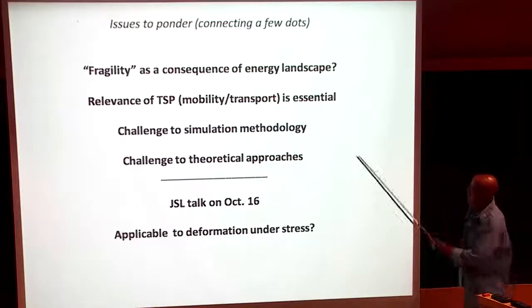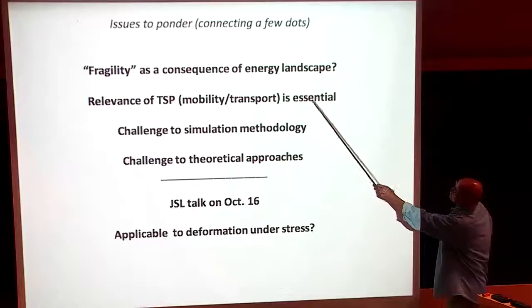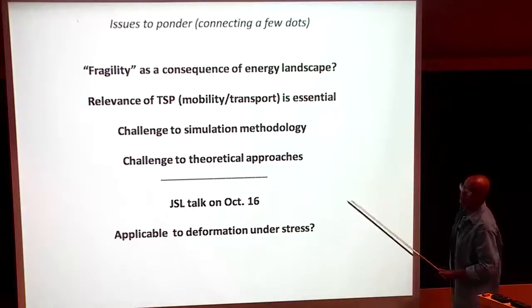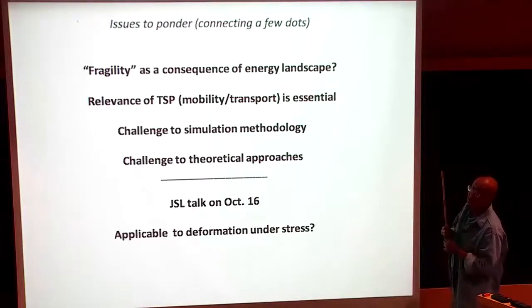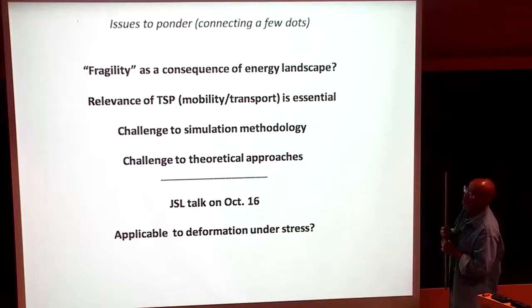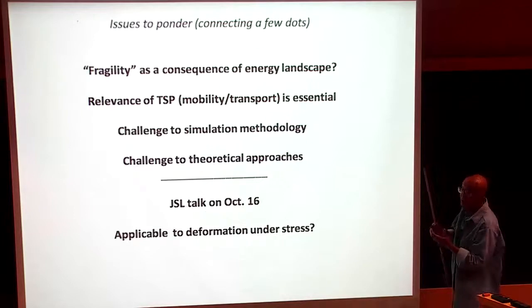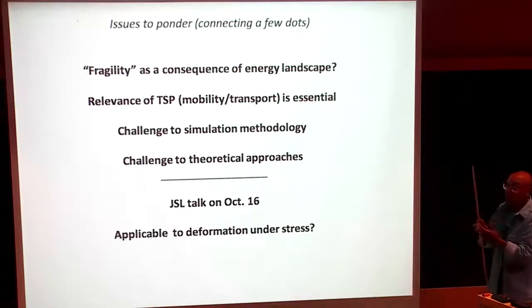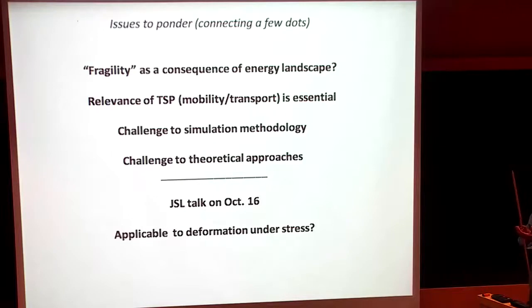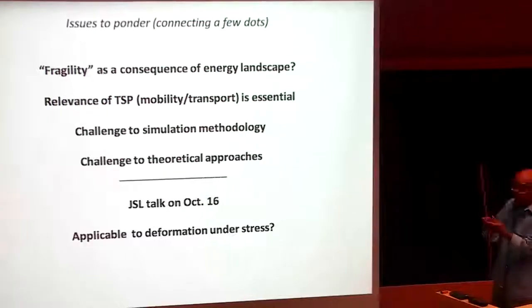So now this is for the glass experts to make any comment. What are the outstanding questions in terms of the fragility nature of the glass transition? Simply stated, from our point of view, all we see is that as you quench a glass-forming liquid to lower and lower temperature, you get into a very rough energy landscape, very, very deep. And as a result of its being very deep, it takes a long time for the system to activate itself, because all you have is thermal activation, right?